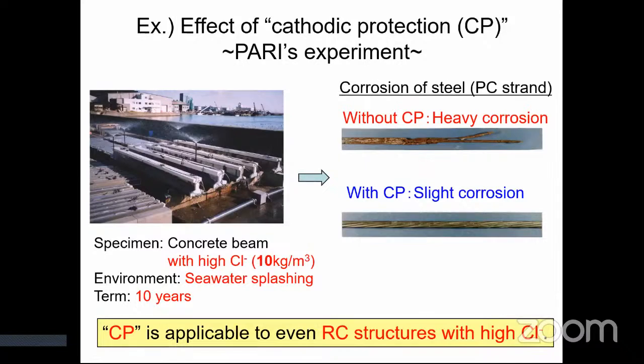This slide shows one example of the effect of cathodic protection in our experiment. This picture shows the exposure site at the Port and Airport Research Institute in Japan. These are specimens: concrete beams with high chloride ion, and these specimens were exposed to seawater splashing for 10 years. The right picture shows the corrosion condition of steel in concrete. Without cathodic protection, heavy corrosion was observed. On the other hand, with cathodic protection, only slight corrosion was observed. These results indicate cathodic protection is applicable to actual structures.